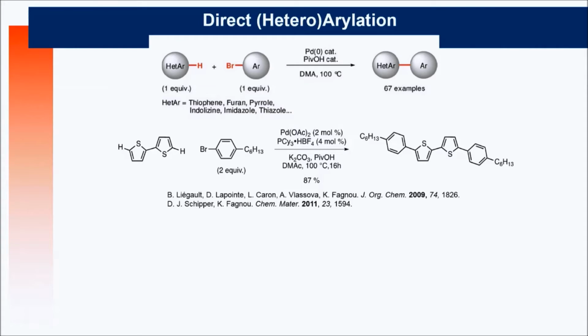I must say that for polymer chemists, this yield is not high enough. If you want to get high molecular weight materials, if you take the Carothers equation, you need a yield of 98, 99% to reach a degree of polymerization of at least 50. If you have a polymer chemistry background, you need a yield of 98, 99% to use a reaction to make high molecular weight materials.